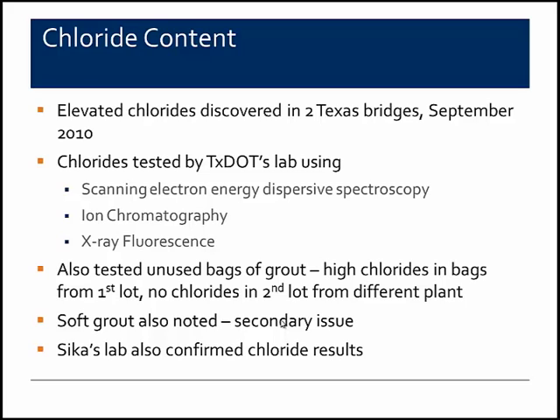They were also able to test some unused bags of grout that had been left over on the project, and did determine that there were high chlorides contained in the bags from one lot of grout, but the second lot of grout that apparently came from a different plant did not have any chlorides. At that time, they also noted some soft grout was formed, and I'll show you a slide of what that looks like. And at the time, they thought that was a secondary issue. Those samples were also sent to Sika's lab, and they did confirm those chloride test results.